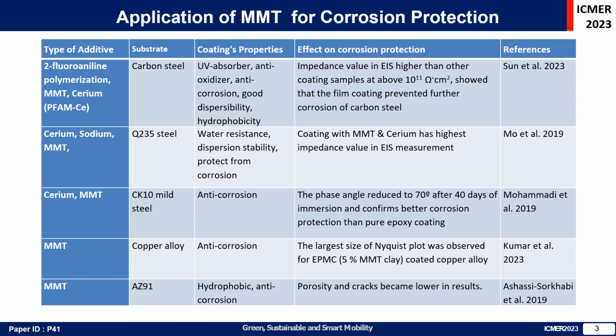Mo et al. used cerium, sodium, and MMT as the additives on Q235 steel. Their coatings show some properties which are water resistance, dispersion stability, and also can protect from corrosion. Their result shows that the coating with MMT and cerium has the highest impedance value in EIS measurement.